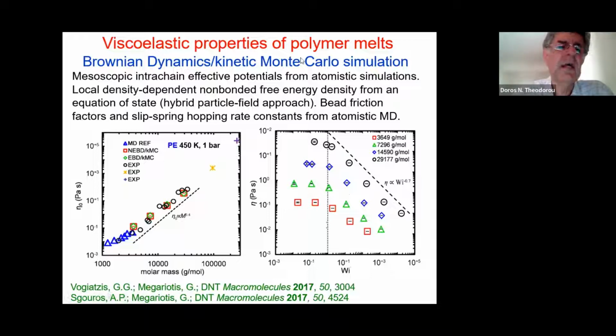For the intra-chain effective potentials, we simply Boltzmann invert the distributions of end-to-end distances of strands as they're obtained from atomistic simulations of relatively small molecular weight melts. So we get something like a nonlinear spring of finite extensibility that describes the intramolecular interactions between the beads. And as regards the non-bonded interactions, we use a free energy density, which is dependent on the local density and derived from the equation of state. In our case, we use the Sanchez-Lacombe equation of state, which describes quite well the volumetric properties of the atomistic simulations and also of experiments.